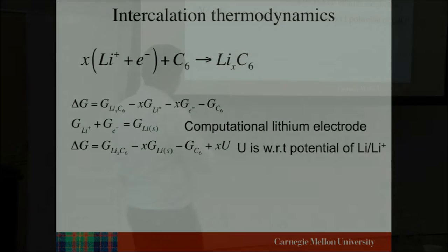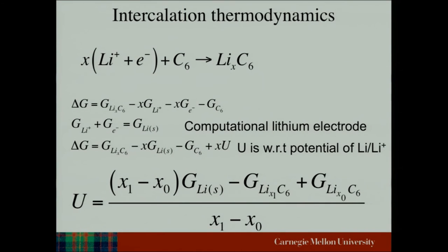This simplifies the expression into a purely chemical process — associating lithium and graphite to form Li_x C6 — accounting for the change in chemical potential of the electrons. When the electron is not at standard state (zero volts on the Li/Li+ scale), all voltages are measured with respect to that scale. This equation determines conditions for equilibrium for different phases of Li_x C6: each phase's free energy leads to a corresponding equilibrium potential when the overall free energy change goes to zero.